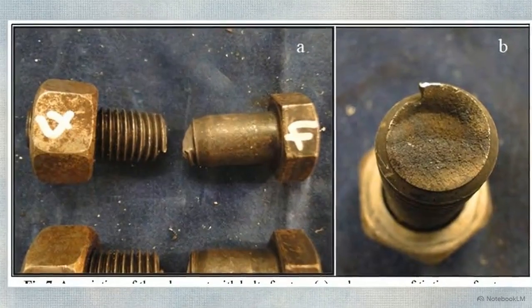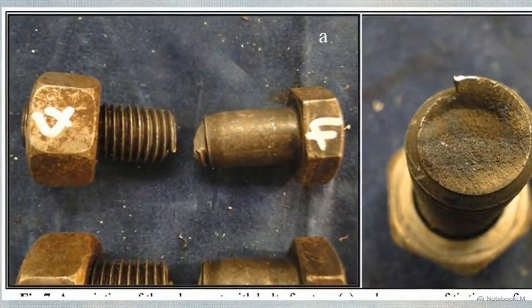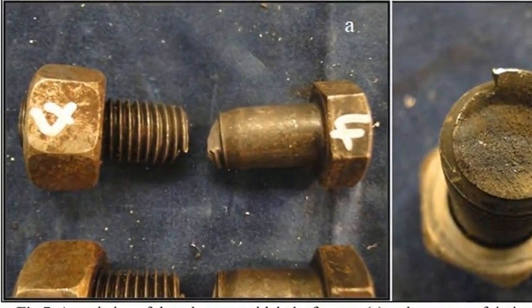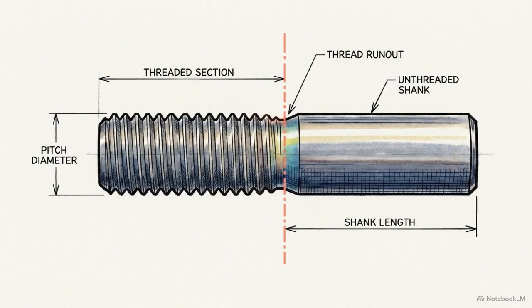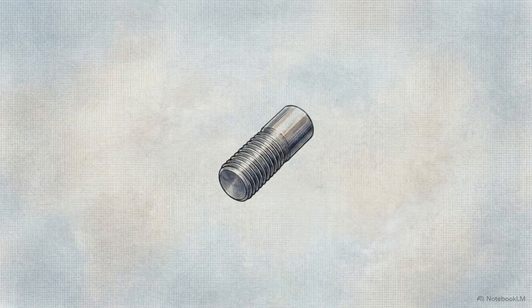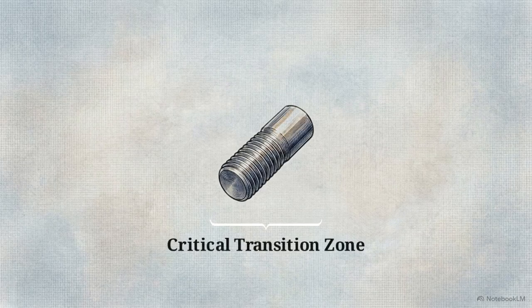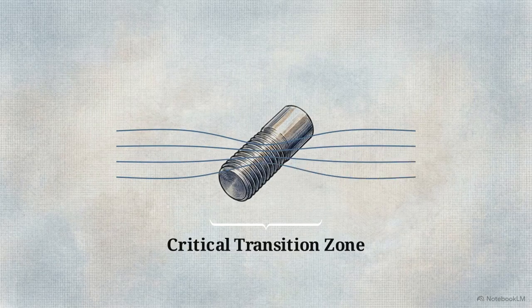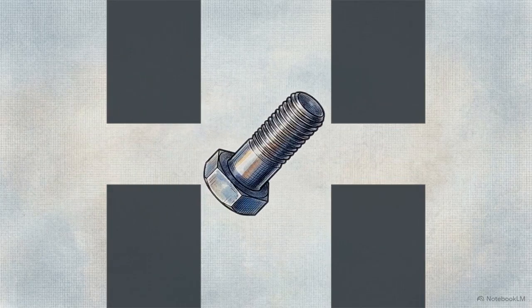This photograph aligns the severed bolt shanks to show precisely where that stress hit its peak. All 8 catastrophic fractures initiated at the exact same axial location, right where the threads end. That specific location is the thread runout. It is the transitional zone where the depth of the machined thread fades out into the solid diameter of the shank, a physical feature that inherently carries a high stress concentration. This animation plots the exact physical location of that runout relative to the assembled heavy flanges.